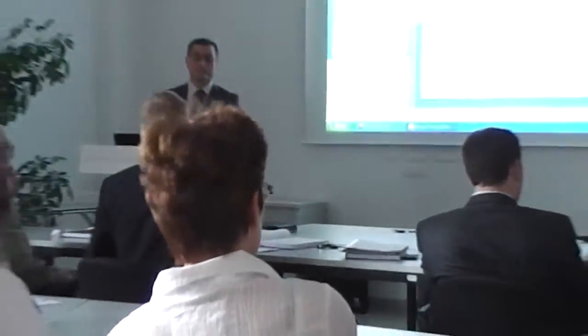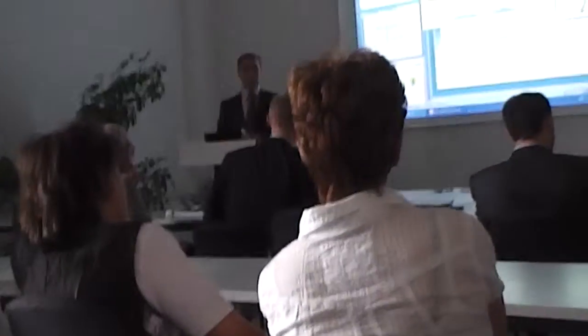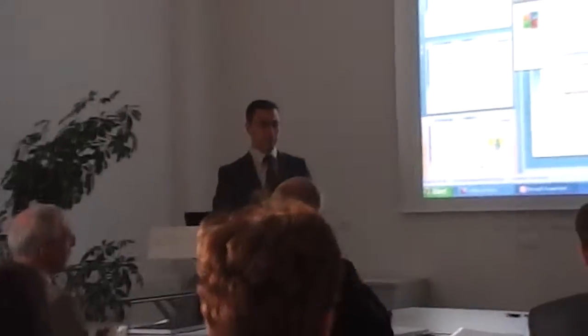Well, I have one question regarding particles and penetration. We saw that you anodized magnesium and aluminum, plasma-like and normal, classical. And then I know there's one picture, not seen over here, where you really fill the pores of the anodized aluminum. And that is a kind of barrier, as you have mentioned. Now back to the particles. If the particles are bigger in diameter than the pores, and the pores of the anodized surfaces are less than 50 nanometers, where have the particles gone?